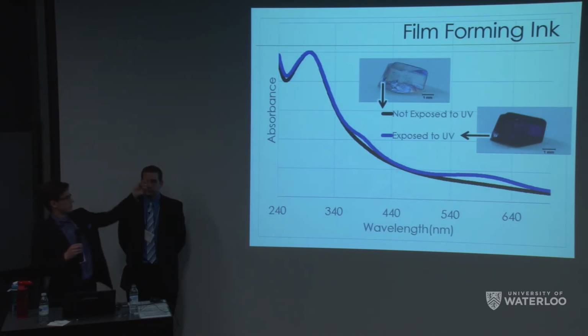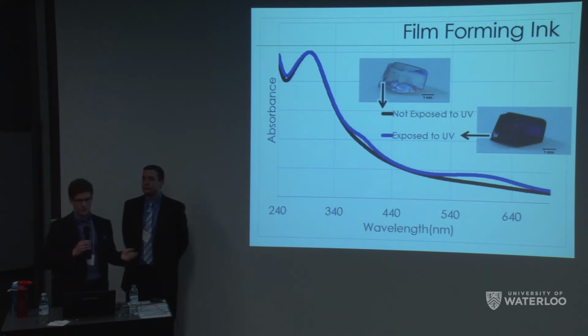So it'll change to its UV exposed or purple state in about 10 to 15 seconds. And once covered with sunscreen and you're outside in the middle of the summer, it'll change back in around 30 seconds, or if you're in the shade in the middle of winter, in about a minute. So for our customers, making a film forming ink doesn't affect their knowledge of when they need to reapply sunscreen, and it allows them to have one application that lasts all day.